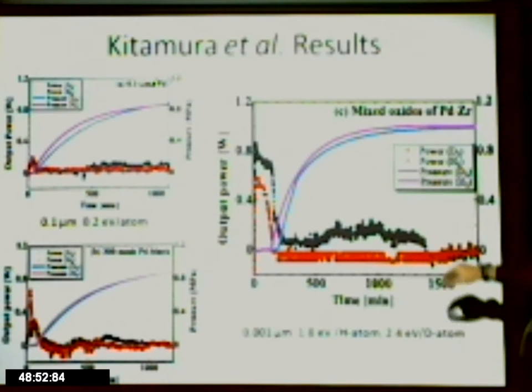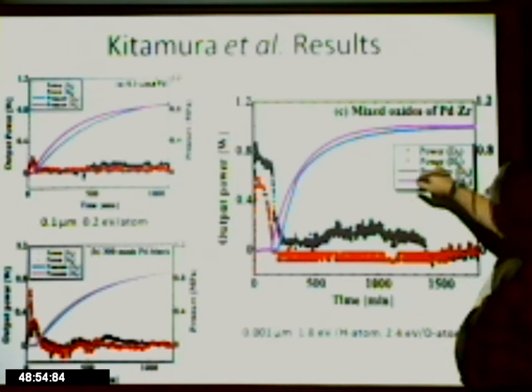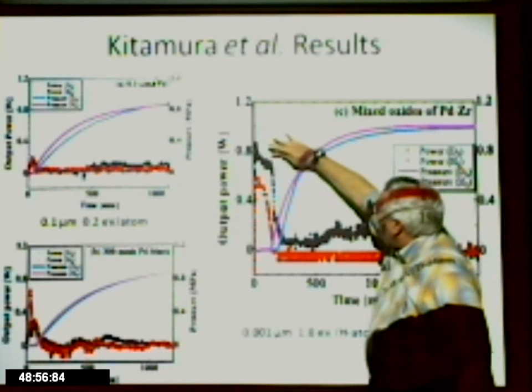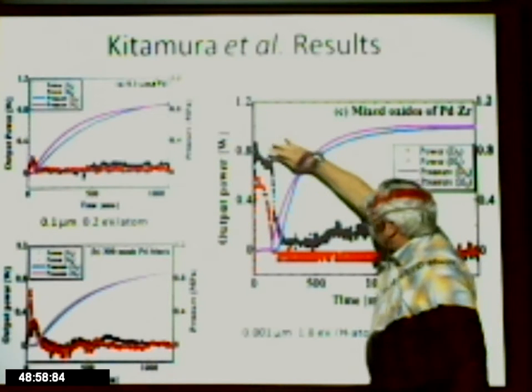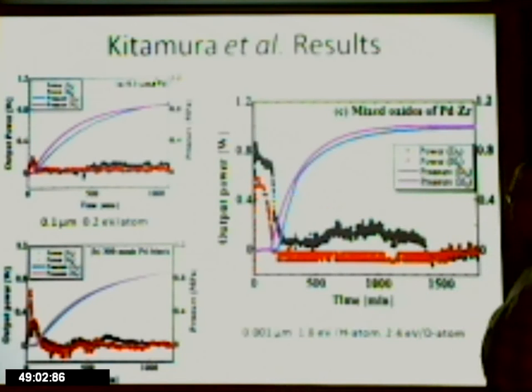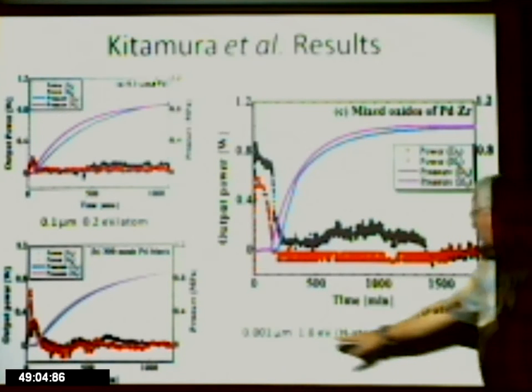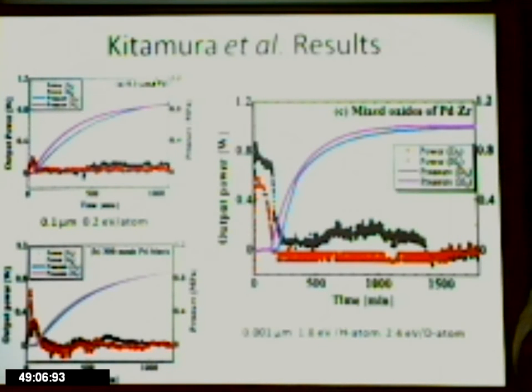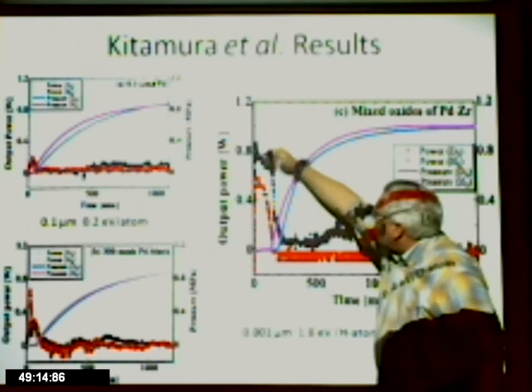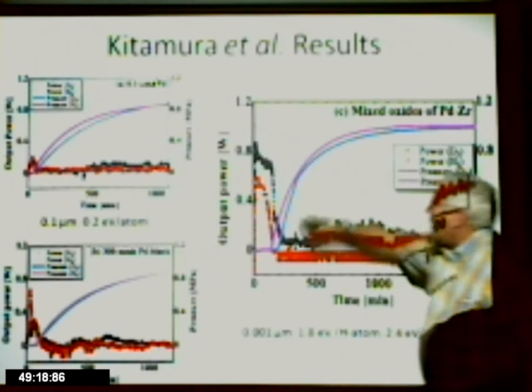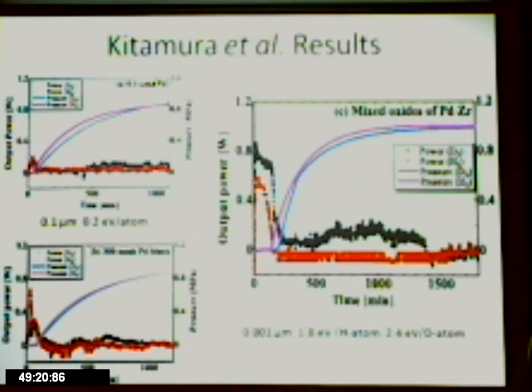And when you do, you see two things that are interesting. One, D2 shows a much higher loading of hydrogen onto the palladium than does H2. It's statistically different. And the size of this is huge compared to what you would see in whole hydrogen passivation of a palladium surface. It's up by a factor of 10. So you have a 10 times greater anomalous heat of absorption. You see an isotope effect between deuterium and hydrogen. Again, these are at near room temperature.